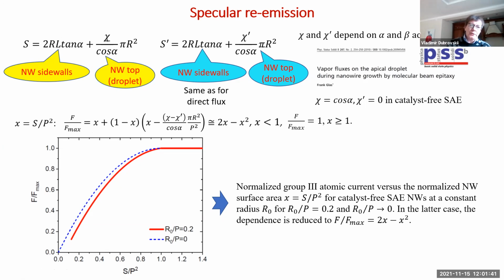And if we ignore completely the top surface, it becomes simple. So it's 2x minus x squared. So basically what we see that at the beginning, if we ignore the top surface, we have twice the direct flux impinging the nanowire side walls. And finally, when x reaches unity, it becomes 1. And this is how F over F max depends on the normalized surface area of the wire, basically. So it always saturates at 1 because this is the maximum.